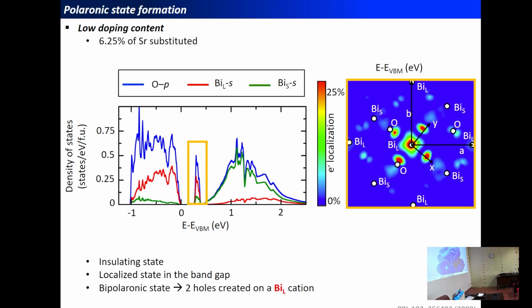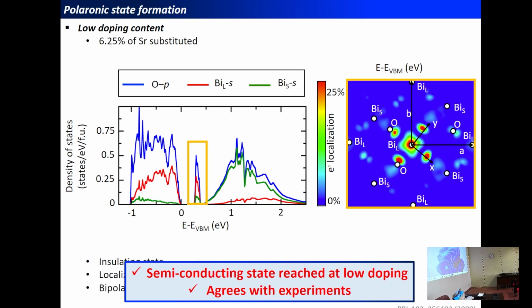And if we look at the partial charge density associated with these states, we end up with an electronic structure which is centered on a large bismuth cation, meaning that we have created holes on what was previously occupied by two electrons in the ground state. So we took some states and just removed the two electrons. And therefore, we have created a bipolaronic state with two holes created on a given large bismuth cation. And this is compatible with previous reports on barium bismuthate that also observed the formation of this bipolaronic state. So at low doping content, in agreement with experiments, we reproduce the semiconducting state of these materials, and this does agree with experimental data.